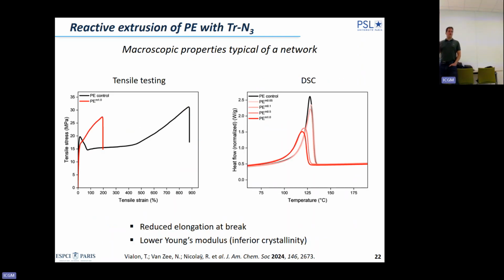And within the 2 or 3 minutes that are left, if we crosslink, so this is a tensile test, starting HDPE, the same HDPE I showed you. So it's a ductile material, and now after crosslinking, of course, as you would expect, we significantly reduce the elongation at break. And here by DSC, we observed that we decrease the crystallinity, which in terms of mechanical properties translates into lowering the Young modulus. We cannot see it here, but it's a bit lower.